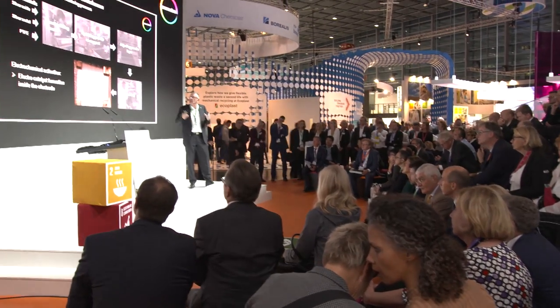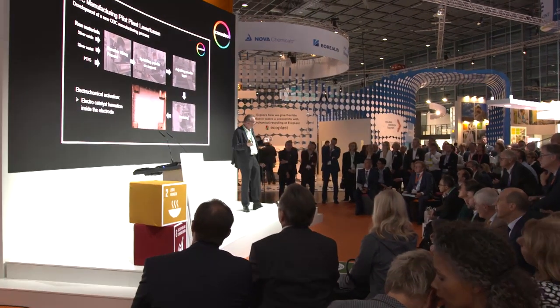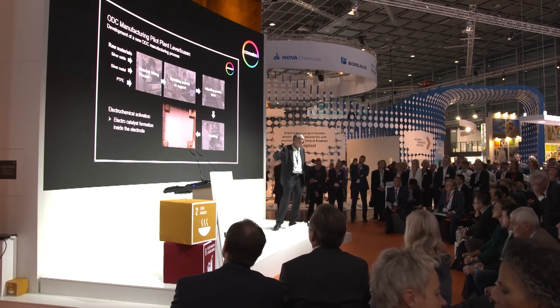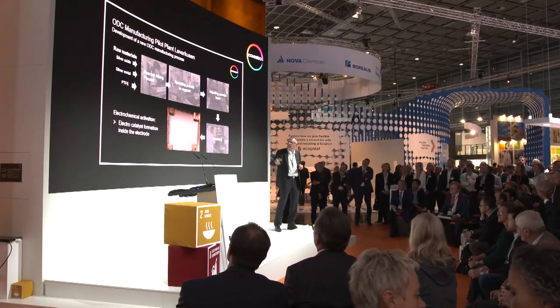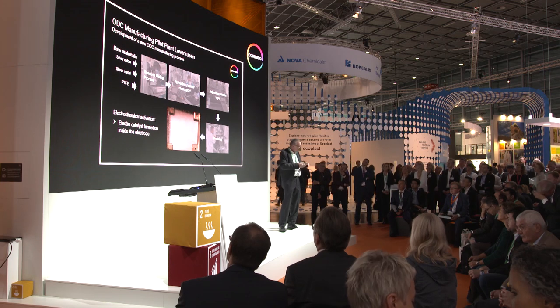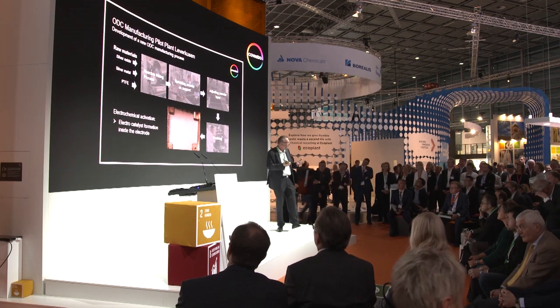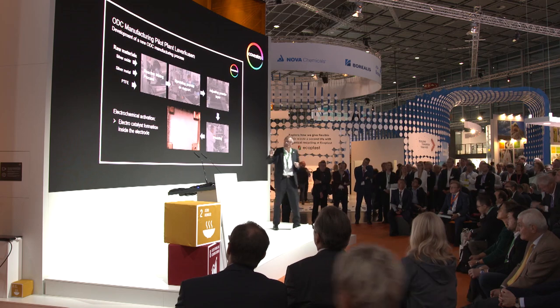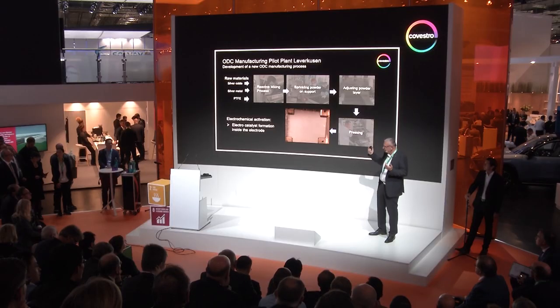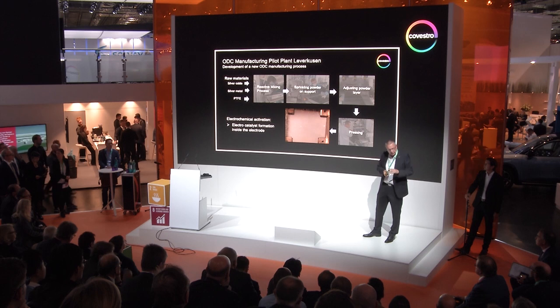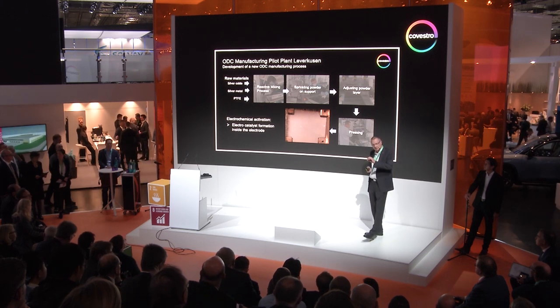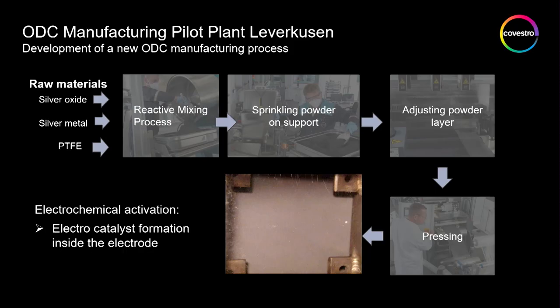So what did we do? We took a powder process, only catalyst powder, and we took a precursor, a silver oxide and silver metal and PTFE, and mixed it together in a dry powder mixer. We call it a reactive mixing process. Out of this, you again get a powder, which is then applied on the support. We adjust a defined powder layer, and we press this powder layer together with the support with a defined pressing force. And the trick of this is the use of a precursor of the catalyst.